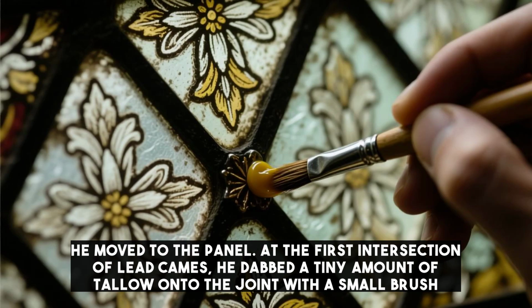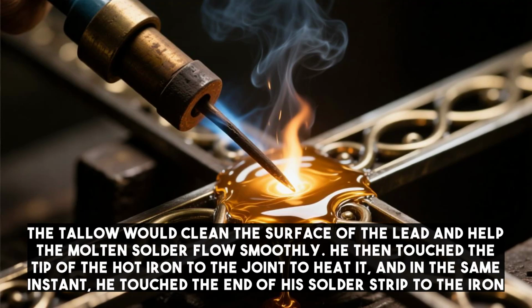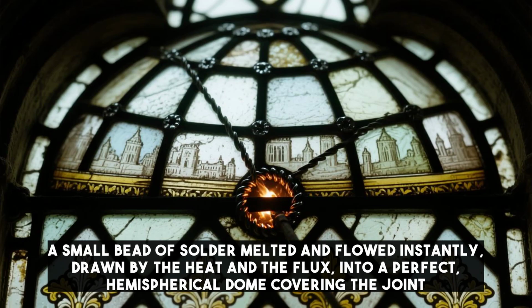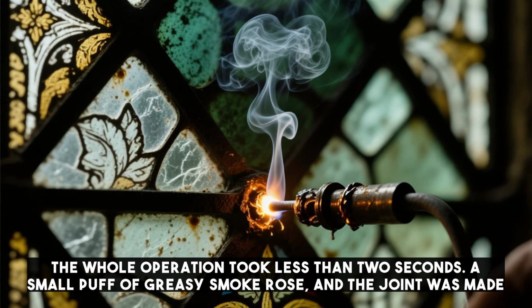He moved to the panel. At the first intersection of lead cames, he dabbed a tiny amount of tallow onto the joint with a small brush. The tallow would clean the surface of the lead and help the molten solder flow smoothly. He then touched the tip of the hot iron to the joint to heat it, and in the same instant, he touched the end of his solder strip to the iron. A small bead of solder melted and flowed instantly, drawn by the heat and the flux into a perfect hemispherical dome covering the joint. The whole operation took less than 2 seconds. A small puff of greasy smoke rose, and the joint was made.